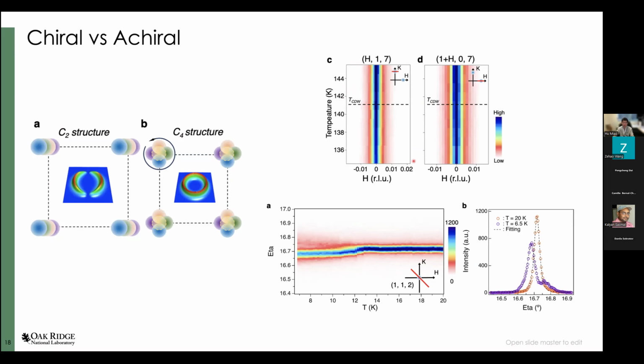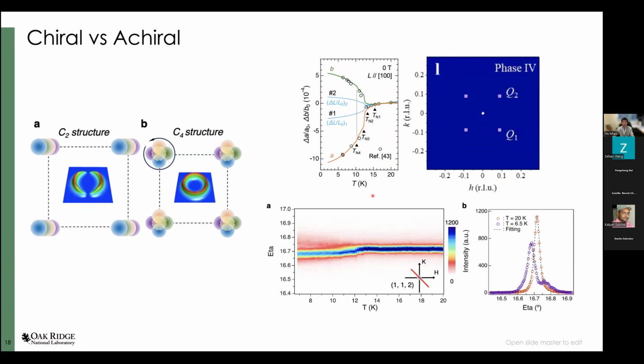Indeed, if you really cool down, you see the four-fold rotational symmetry breaking around 12 Kelvin. So that again confirms that below the CDW transition temperature at 140, there's no four-fold rotational symmetry breaking. This is consistent with thermodynamic measurements and the neutron measurement. So based on this study, we believe we can rule out the nematic charge density wave, and we have a C4 rotation-preserved charge density wave in europium aluminum 4.